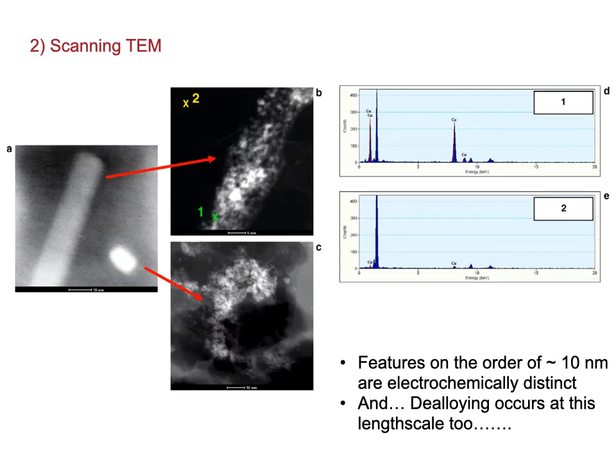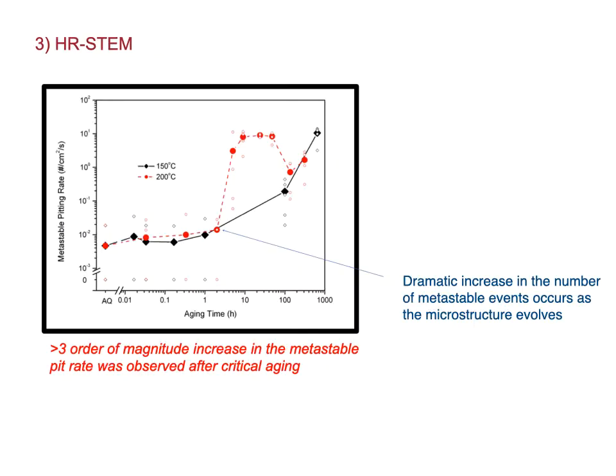Following exposure of the TEM foil that we saw in the previous image to sodium chloride for a very short amount of time, so we're talking some tens of seconds here, it was shown that the de-alloying that we mentioned earlier could occur at the finest of length scales measured at the time, and that was able to also be analysed by energy dispersive X-ray spectroscopy, and so it looks like little stuff de-alloys too, which we now know.